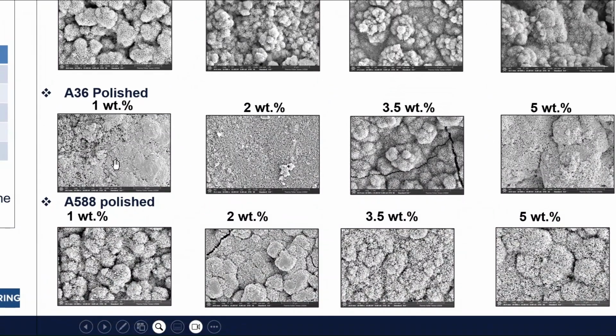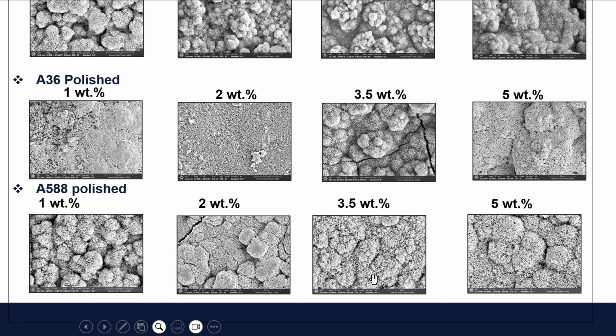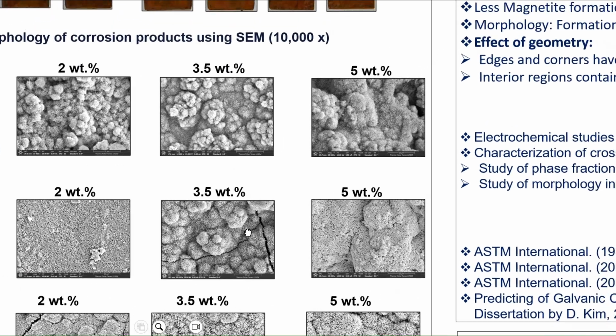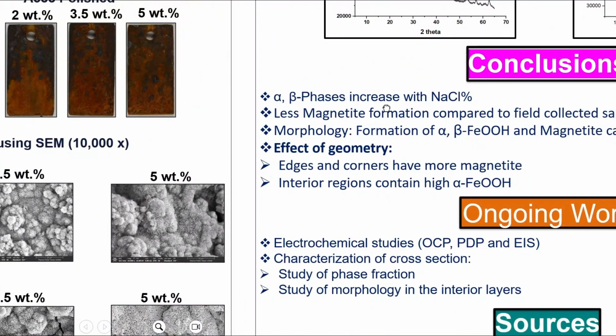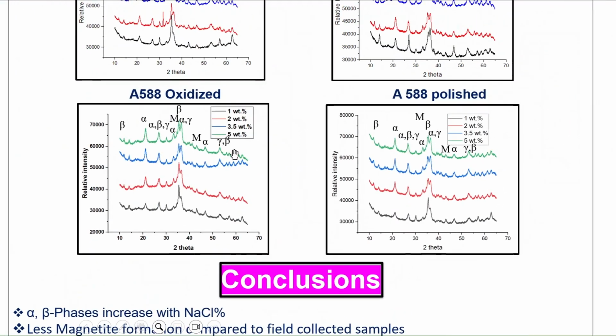And this corresponds to a small cotton ball with dense packing. So this can be called magnetite, and this is again alpha FeOOH. This is magnetite, and this is beta FeOOH. This is alpha FeOOH, and this is magnetite. So SEM is used for confirming the presence of different products.